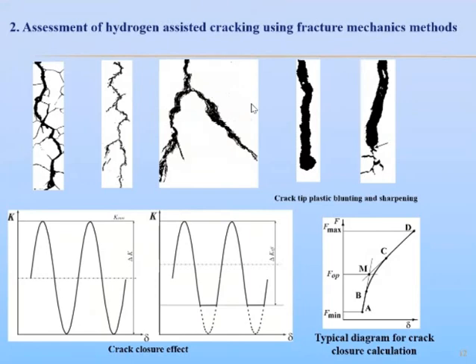But they can have some influence for starting cyclic loading. Another factor that should be taken into account is the crack closure effect, which concerns fatigue crack growth only and consists in prevention of crack closure during part of unloading. The real stress intensity factor range is less than the nominally calculated. Just the effective stress intensity factor range is the real mechanical driving force of fatigue crack growth.